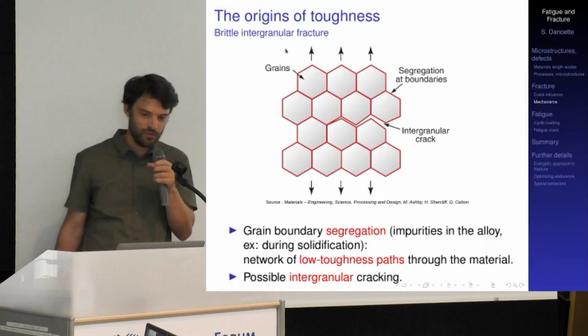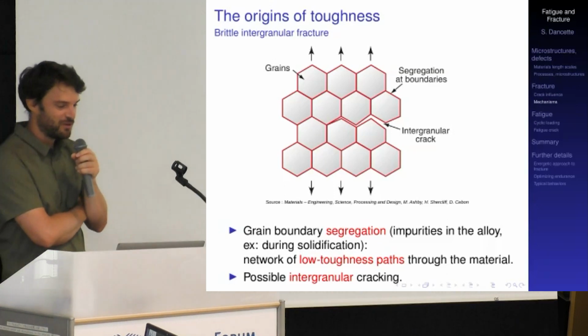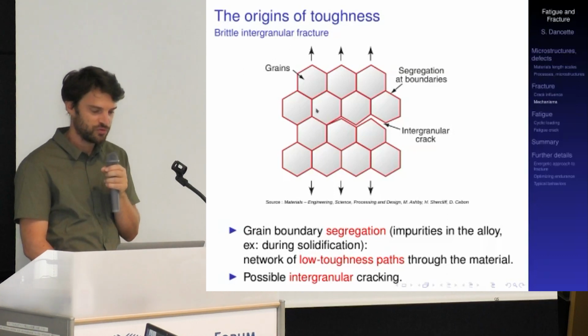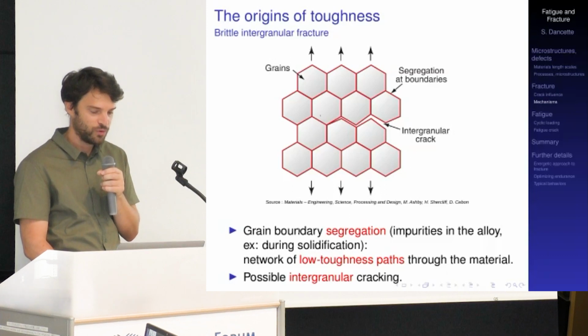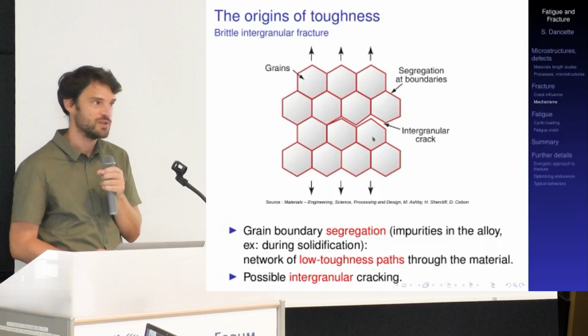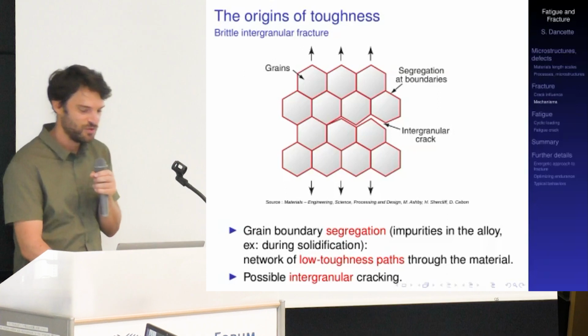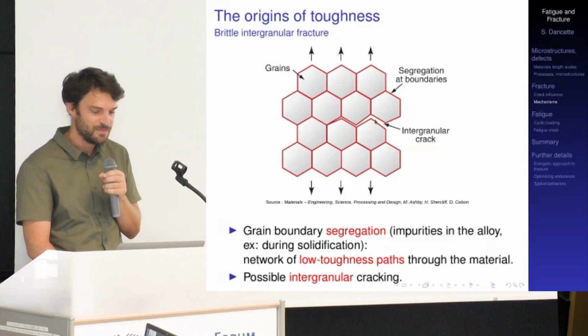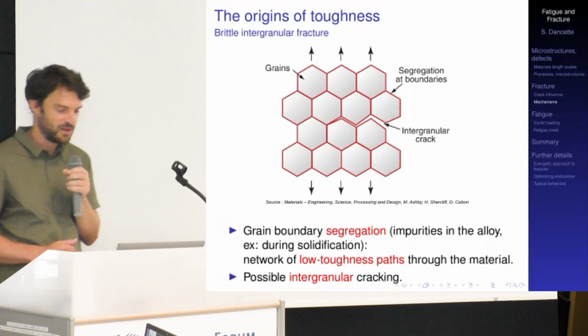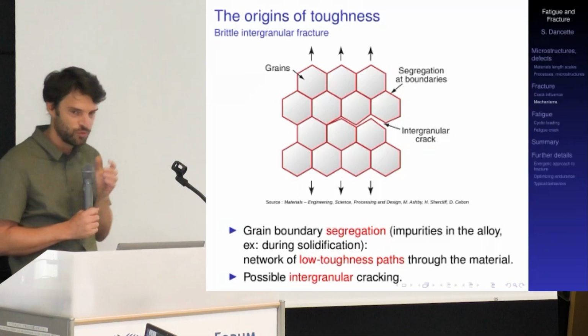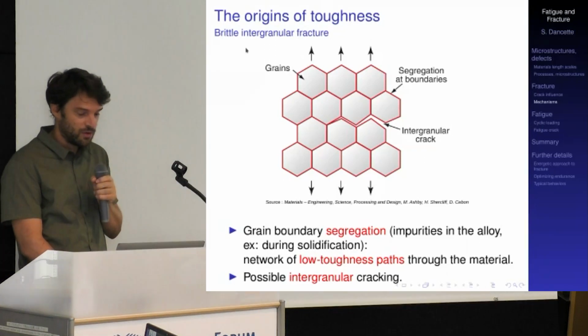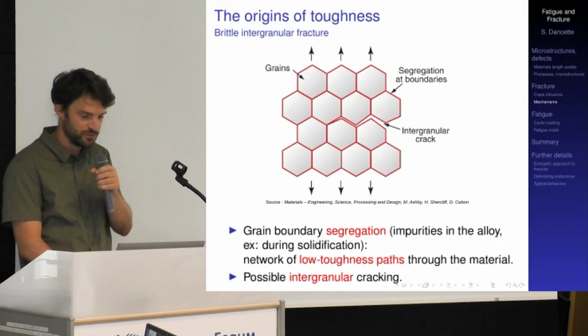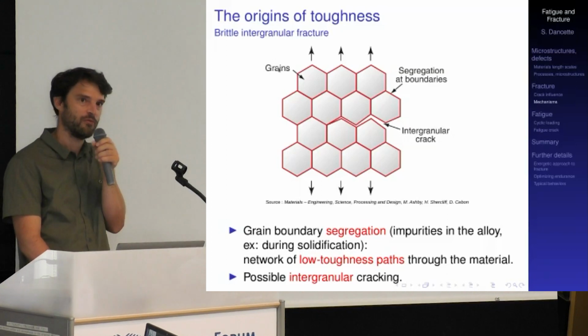I guess my colleague Nicolas will talk a little bit more about it later. In the case of intergranular fracture, because of the grain structure of most ceramics and metals, if you happen to have some grain boundary segregations, impurities for example in the alloy that tend to develop at the grain boundaries, and if these impurities are brittle, which is not uncommon, then you have an easy path for the crack along the grain boundaries. This might be accelerated by the environment, for example a corrosive environment. So the easy path for the crack is at the grain boundaries because of these segregations or impurities that may be present in alloys. Intergranular cracking is another example of brittle material fracture.